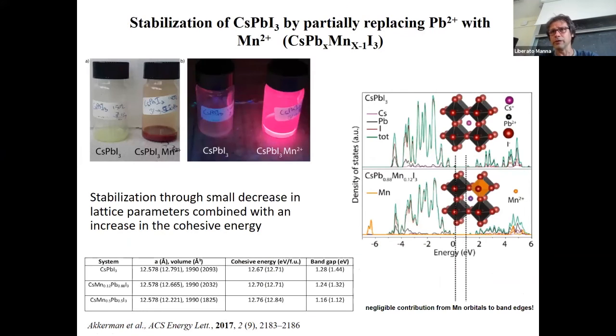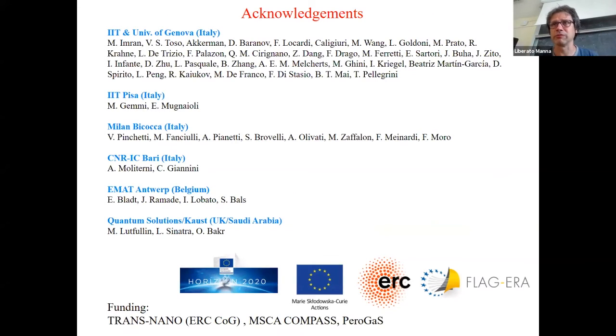And then, the alloying with manganese increases the cohesive energy, so it stabilizes the overall energy of the nanocrystals, and also manganese introduces orbital states which are either very high or very low compared to the band edges. So in the density of states, there is not much contribution of manganese states in the gap or the band edges, and this is why basically they optically behave as the standard cesium lead iodide nanocrystals. So with this, I finished my presentation. I thank all these people and different groups, funding agencies, and you for the attention.